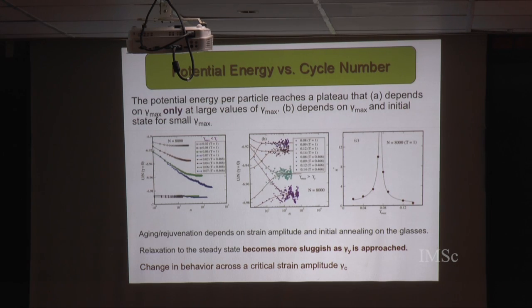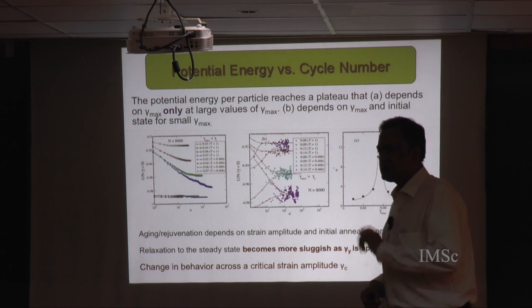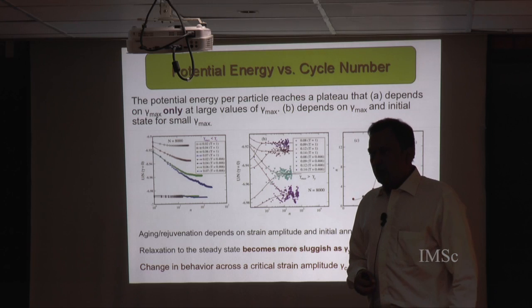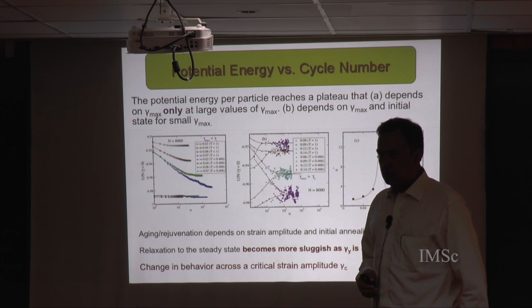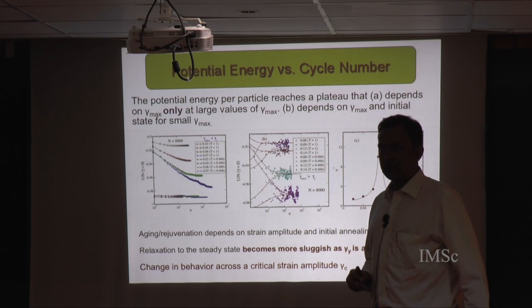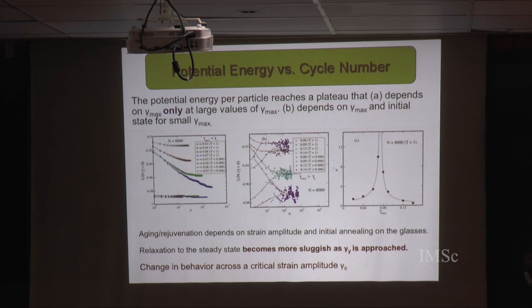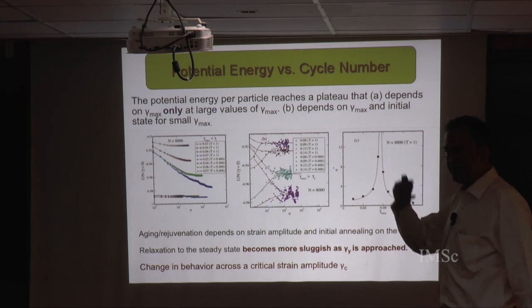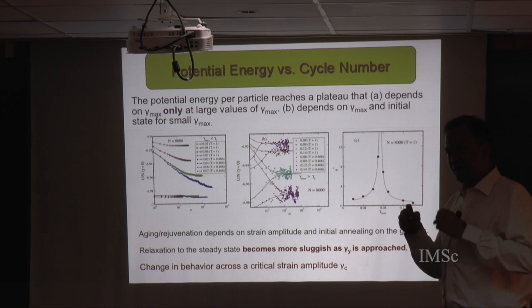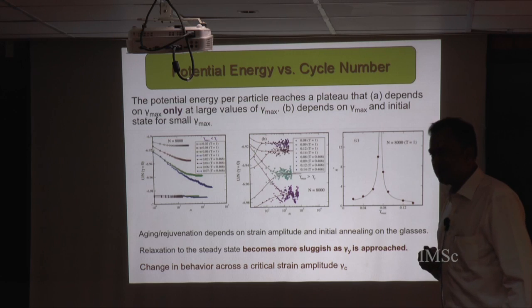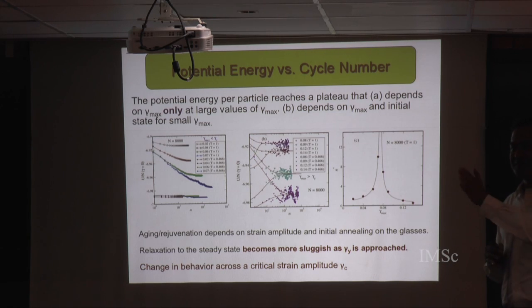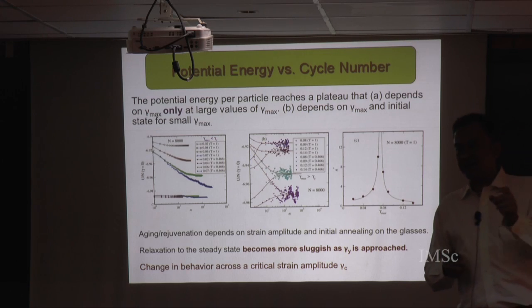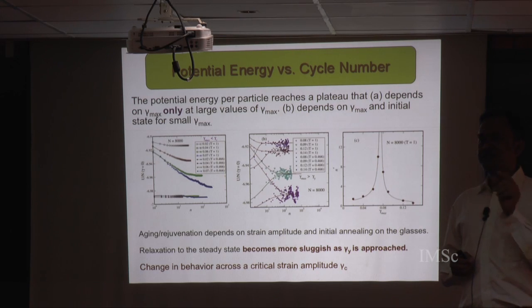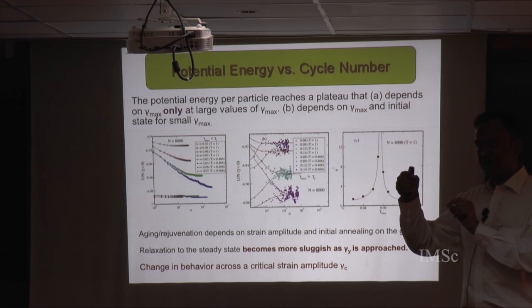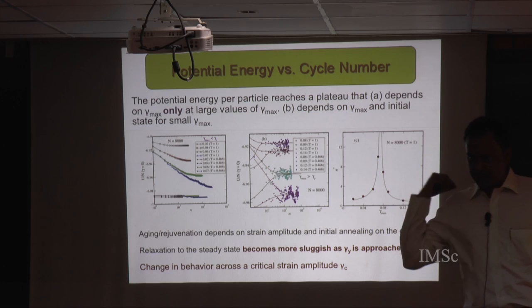How does gamma max depend on the system size and the energy state? The gamma max where you have that divergence depends marginally - you will see some data. There is a little bit of size dependence, but we also don't have infinite precision here because we're going up in steps of 0.01. Also, we've only sampled some discrete values. So within that discrete set of values, there is some change because of system size that you observe, but very marginal. I'll show you data for that.